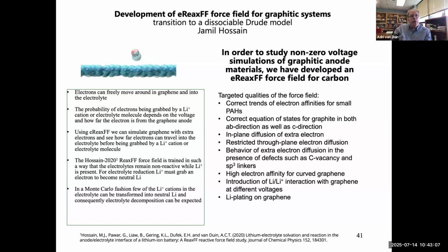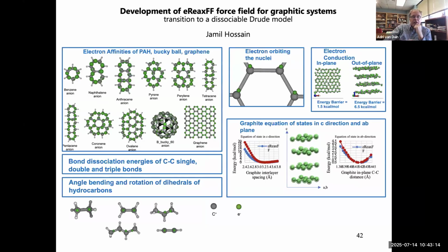And now we also can do voltages, because we can simply add more extra electrons to the graphite and allow them to move through the graphitic material. So this was developed against a pretty big training set with all sorts of polyaromatic hydrocarbons, where we included the electron affinity and ionization potential. We also trained it against in-plane conduction and out-of-plane conduction in graphite, and against the basic graphite equation of states.